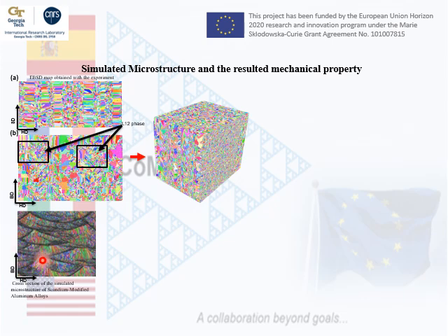between columnar grain zones, we observe this fine structure of grains, and in this zone we expect to see a higher density of second phase particles, right? And at each of these second phase particles, we expect to have one or more crystals nucleating, simply because the work of nucleation is also being reduced. Okay. Here in the simulation, it is difficult to see, because we have different representations here, but actually we have a relatively good agreement with the simulations.